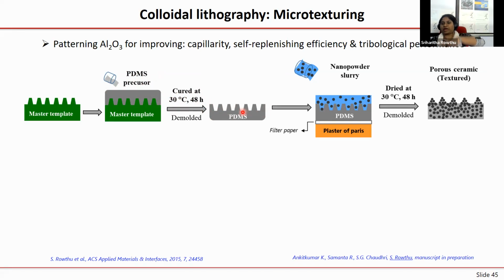Now I'm going to pour my slurry. Remember, we have made our alumina slurry, the deagglomerated slurry. That slurry is what I'm going to pour on the PDMS, and again carefully dry it. If you are not very careful here, you are not going to get your results. In fact, the first time I did it, I was able to get it. Later on, I was not able to get the reproducibility. That's when I had to do a thorough, in-depth scientific study of the drying process. I'm going to talk about that scientific part of the drying.